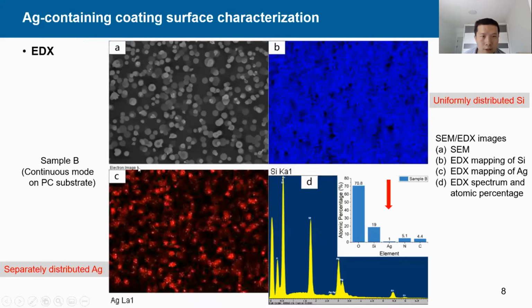And when we check the EDX of sample B, especially when we look at figure B, this is about the silicon map, and it's almost uniformly distributed on the surface, which reveals that the aerosol is also covered by the silicon formed by the polymerized HMDSO. And when we check the EDX map of silver, we can see the silver is scattered, mostly located in the spherical structures. The observed area also shows that 1% of silver in the coating.